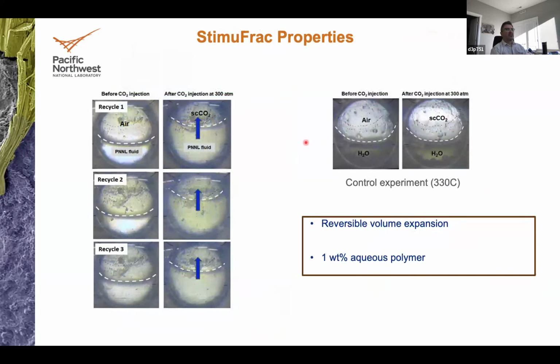Since the reaction is reversible, like I showed you by NMR, nuclear magnetic resonance, you can see that the volume expansion takes place at 300 atmospheres. This is 4,500 psi at 300 Celsius, and then you depressurize and you get back the polymer solution. Then it expands again with repressurizing with CO2, and then you get a polymer solution. We did this several times. You get slightly less expansion, but I think what happened is you have a little bit of irreversible reaction going on. Other than that, most of the reaction takes place via a reversible interaction between CO2 and the polymer.